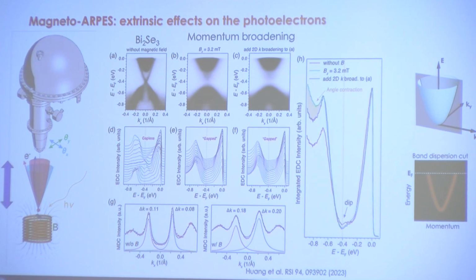Basically, he realized that when we apply a field, even though the energy is unperturbed under a magnetic field, there is a broadening in the momentum direction of the spectral weight. And because these cuts are taken in these slices, the momentum broadening happens in all directions isotropically, both within the plane and also in the perpendicular direction, right? So what that means is that some of the spectral weight from the Dirac point actually gets spread out to the direction perpendicular to the slice. So that's why if you look at the EDC, the energy distribution curve, the field looks like it's making a dip, but actually this is really due to this.